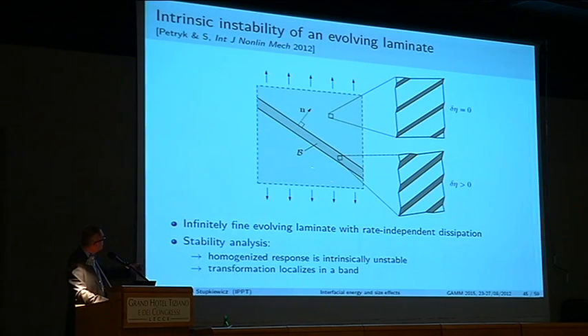It will localize into a band, so if you think of a loading case, of a loading of such a specimen of the material, one part will stay without increments of the volume fraction, and only you would have a localization band in which the deformation would proceed. So it's not good news for us, because we like laminates. We do all our modeling in laminates, and then it doesn't work as we assumed, right? Because we have this localization.